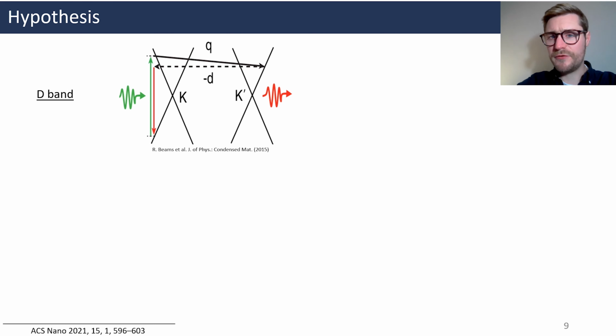So, quick reminder, in graphenic materials, the D-band comes from a double resonance effect. First, a photon is absorbed, which sends a charge to an excited state. A first inelastic scattering event involving a phonon sends a charge to a second state. To be able to recombine, a second scattering event, an elastic one this time, is needed. So, an elastic backscattering is needed. Then, why does this backscattering event occur with cavities? We proposed three hypotheses for that.